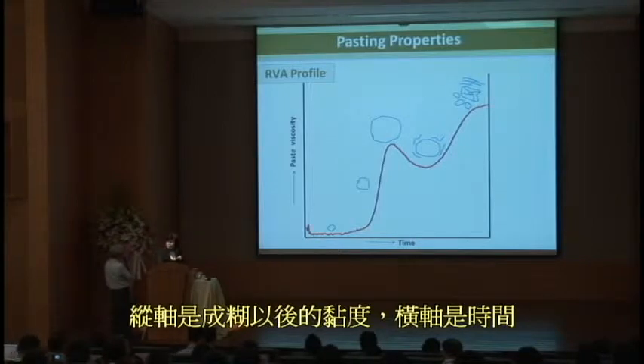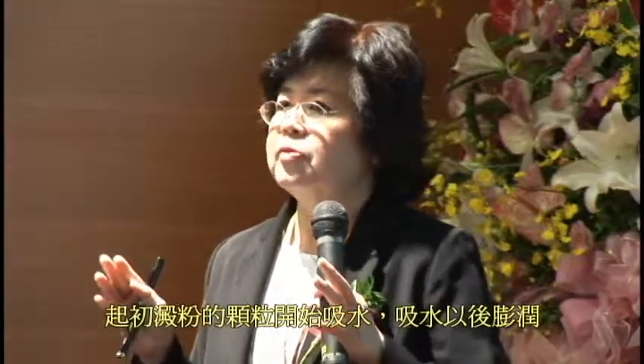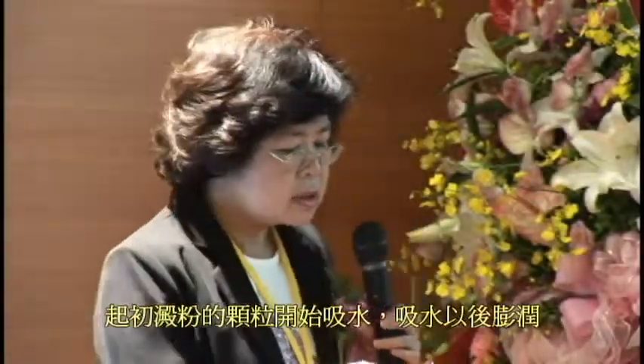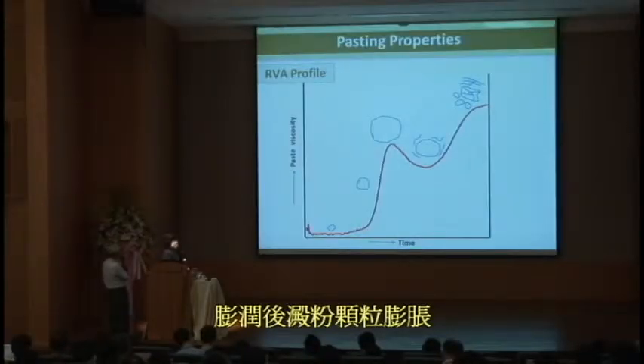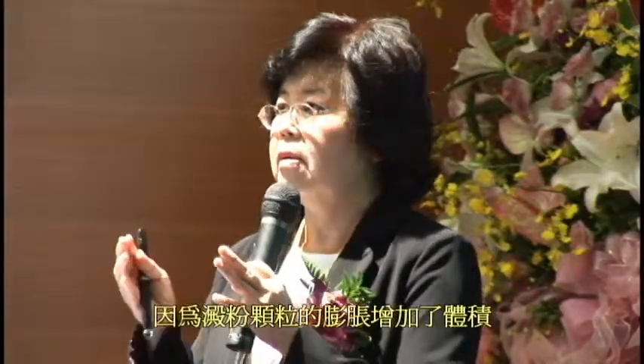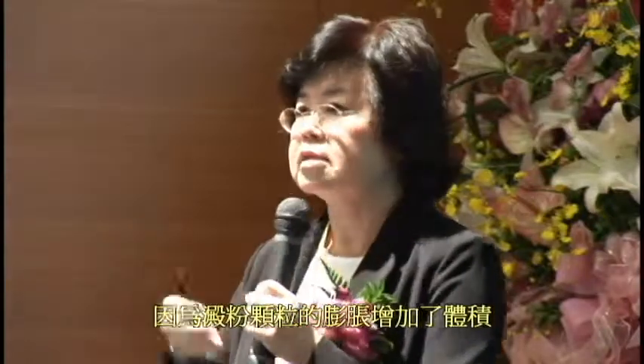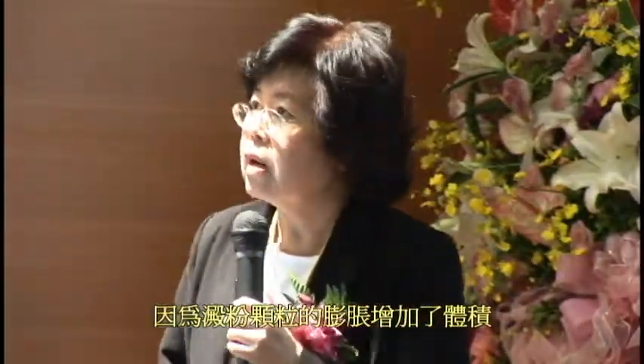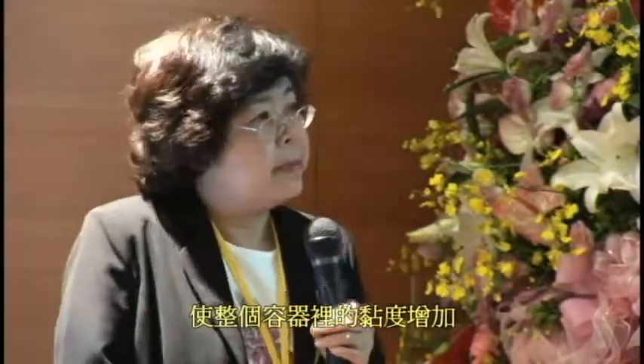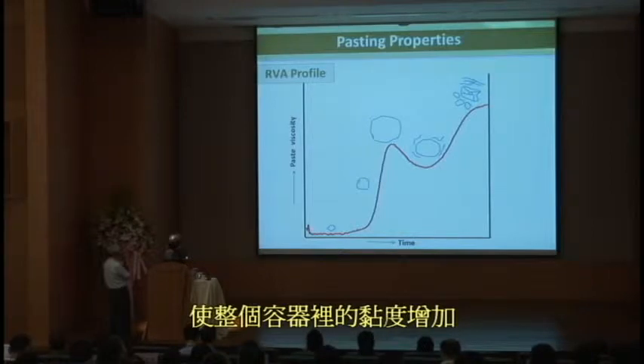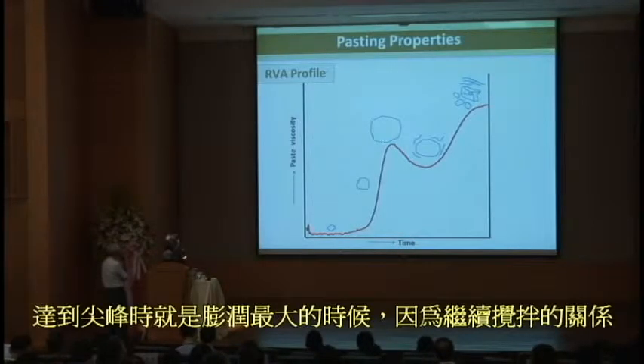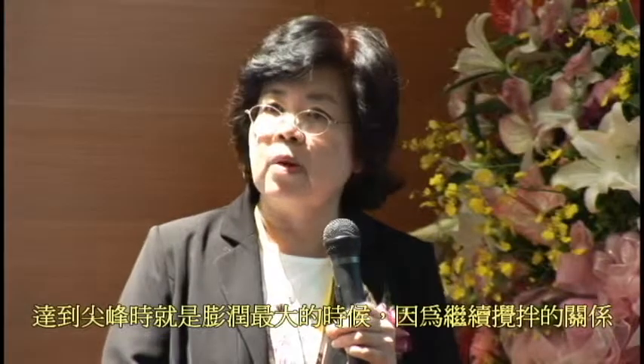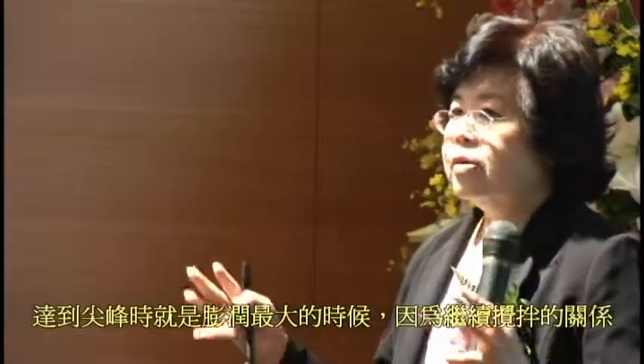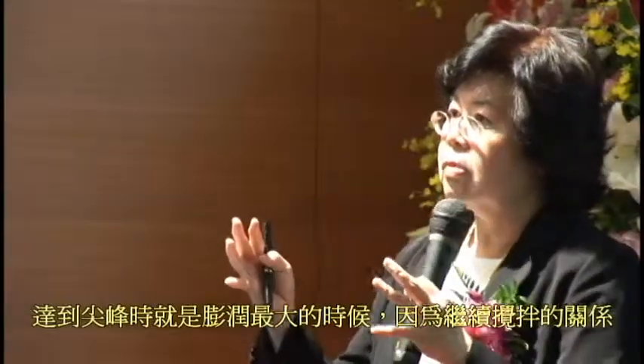So I would like to explain a little bit about this profile. The temperature profile is from the previous slide. We start at the low temperature. The starch granules swell a little bit, not much, when they absorb the water, but the temperature has not increased yet. When we increase the temperature with the program of the equipment, the granules swell more and go to the maximum swelling. They swell the most because the volume of the granule increases to the maximum volume. It causes the viscosity to get the highest.